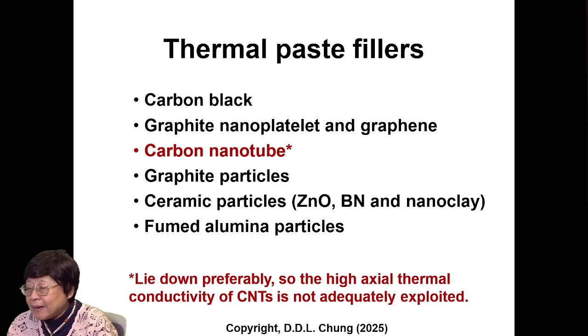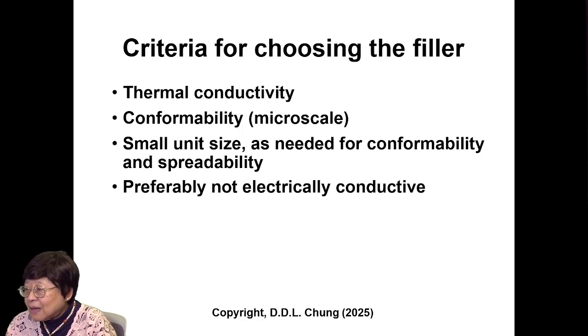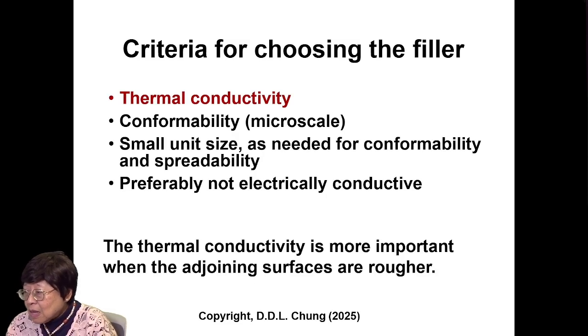Next, consider carbon nanotube. They tend to lie down. So the high axial thermal conductivity of nanotubes is not adequately exploited. The criteria for choosing the filler include thermal conductivity, conformability in the microscale, small unit size as needed for conformability and spreadability, and preferably not electrically conductive. The thermal conductivity is more important when the adjoining surfaces are rougher.